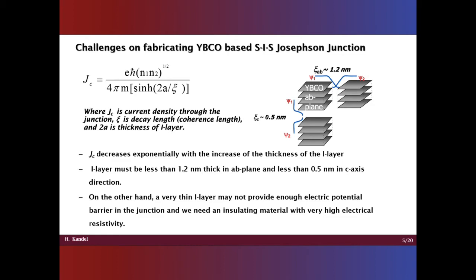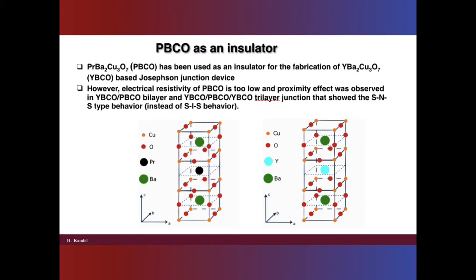Finding an effective insulating material for our device is one of the first challenges our group faced. Numerous attempts at fabricating different types of junctions using PBCO as the insulator have been made, though without successful results. The junctions made with PBCO were either too low in electrical resistance, possessed minimal value of IC, or had a TC value below the liquid nitrogen boiling temperature, which is 77 Kelvin.